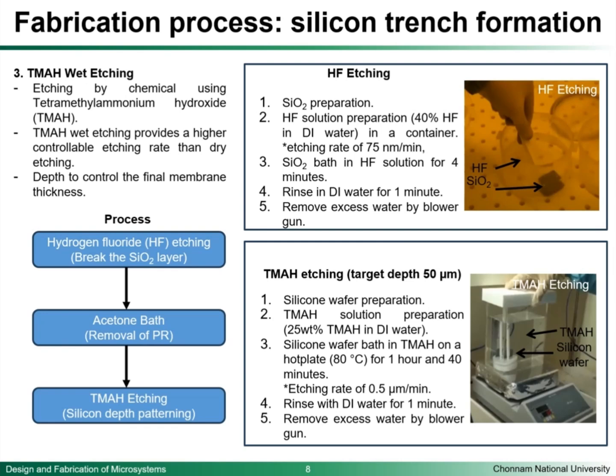And then the first one will be the HF etching. So we will prepare our silicon dioxide layer, and then we will make a solution of 40% HF in DI water. So the etching rate will be 75 nanometers per minute, and we will etch it for 4 minutes, and then we will rinse it for 1 minute in DI water. And then to remove the excess water and also the HF, we will use a blower gun.